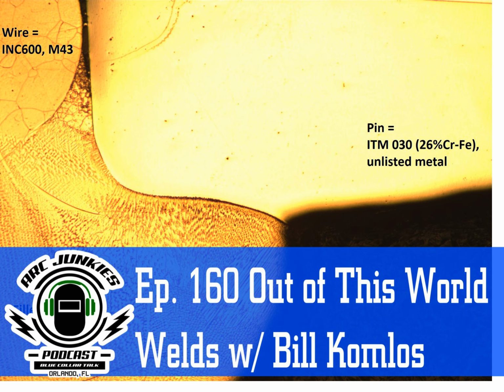And I get fantastic Charpys, but I don't dare tell anybody how I do it. I've been making money telling people who say, how come my 6061 aluminum test fails? I said, you're baking the weld. Get yourself the D1.2 aluminum code and look at section 5 there under fabrication. There's holding temperatures and times for all of these 50 series, 60 series aluminums. You can't hold it at 350 degrees for more than 10 minutes, otherwise it overages and you lose all your strength.